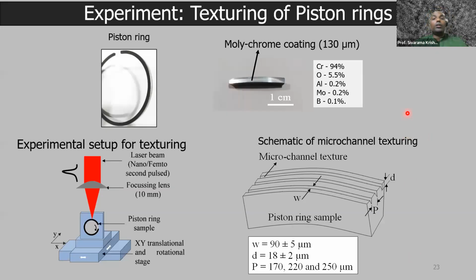Okay, so what exactly did we do? So we took piston rings as is from our industry partner, India Pistons. These were molychrome coated, and the coating itself is about 130 micrometers. So we need to be delicate about what we are doing over here. The experimental setup is quite simple. We fix the piston ring on a sample holder, which is suitably designed for that. And then we translate the sample while we rotate it in the Z direction, almost as if we are binding a rope around a cylinder.